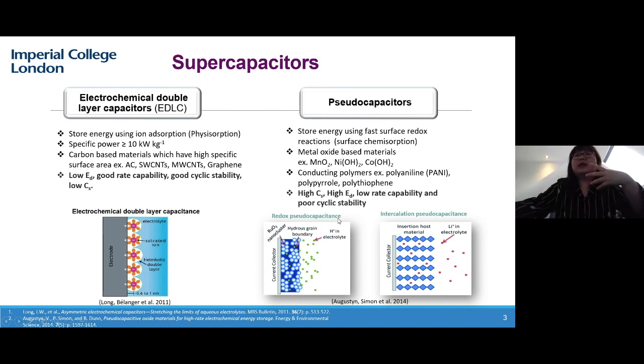They have two mechanisms, which are the redox pseudo-capacitance and the intercalation pseudo-capacitance, through metal oxide materials such as nickel hydroxide or cobalt hydroxide. However, because these kinds of material can decompose easily from time to time, they suffer from poor cyclic stability and low rate capability.